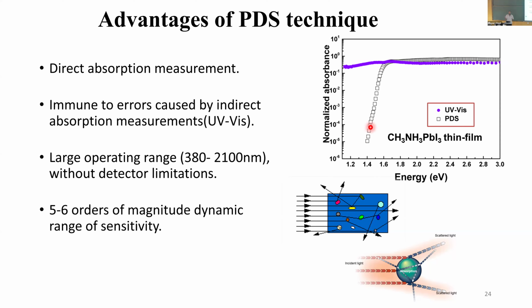But if you consider optical absorption, as in the transmission-based measurement, the light may never come through because it was not absorbed, or it was absorbed but can get scattered away all around, it can reflect. So you have associated losses. It can also be wave guided, a lot of things are there in the samples. So even if your sample is very scattery, the PDS can still look at it. It only measures absorption when you produce that heat, and that only happens not otherwise.